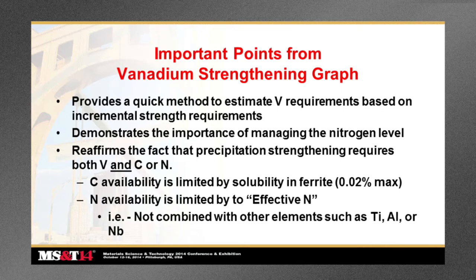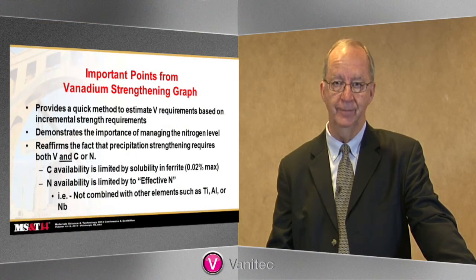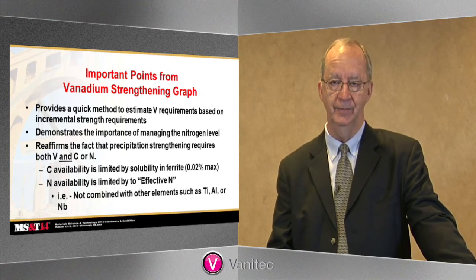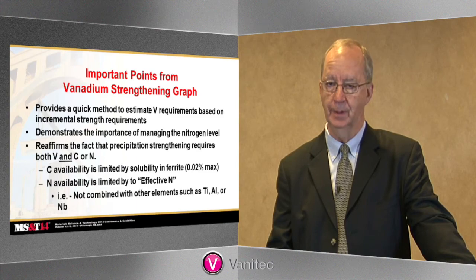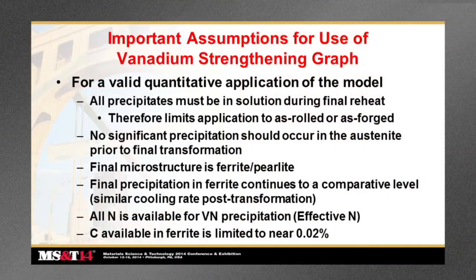Carbon availability is limited by the solubility in ferrite, and typically that's a 0.02% max. Nitrogen availability is, of course, limited to the effective nitrogen level. In other words, it's not necessarily just the total nitrogen, because other elements may combine with the nitrogen prior to it being available for vanadium nitride precipitation in the ferrite. These elements that in fact do compete with vanadium for combining with nitrogen are titanium, aluminum and niobium. For valid application of this model, we have to keep certain things in mind.